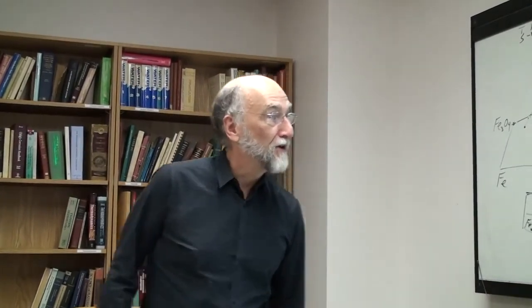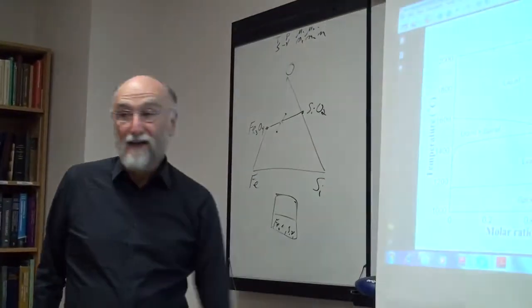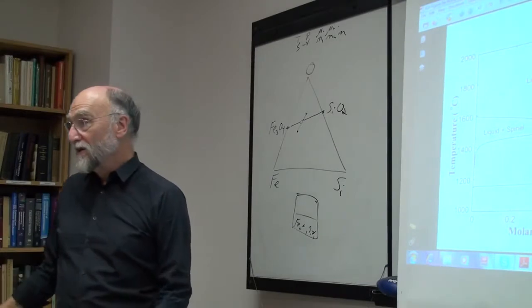So when somebody says the Fe3O4 SiO2 diagram, it really isn't exactly that. The liquid is not going to be exactly Fe3O4. It can contain some Fe2 plus, whereas one phase contains a little less iron and the other a little more. The spinel phase isn't exactly an M3O4, Fe3O4 phase. It can contain excess oxygen.